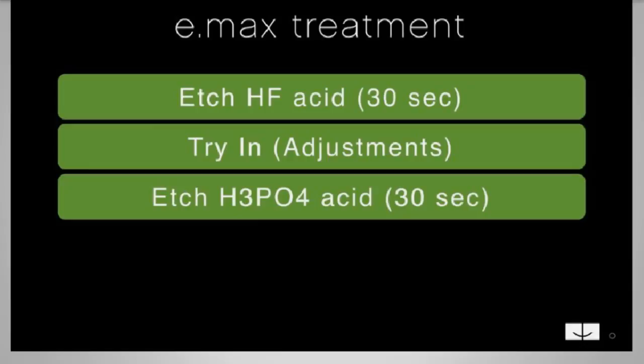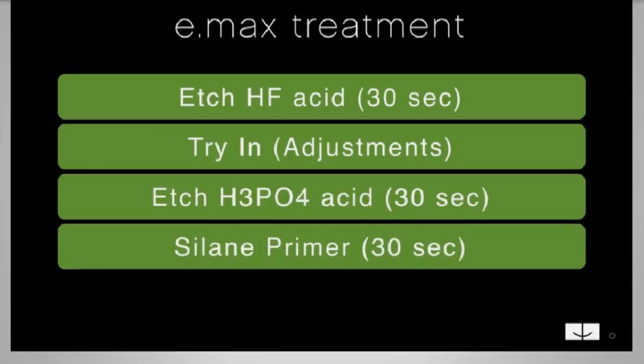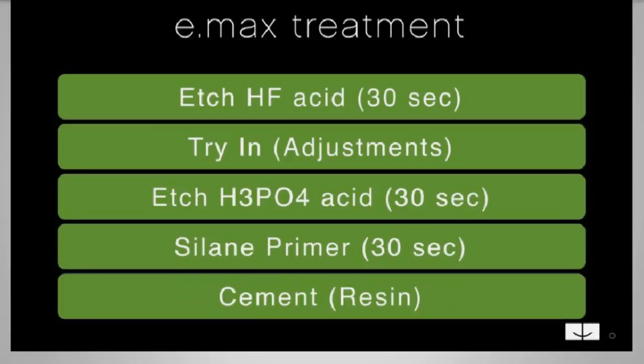Okay, so I etch it with hydrofluoric acid, and then I try it in the mouth, and then I etch it with phosphoric acid to clean it up. And then I put my primer on, and I like to use multiple coats, right? At least for 30 seconds. I let it dry, maybe air dry it a little bit, and then you can use your cement.